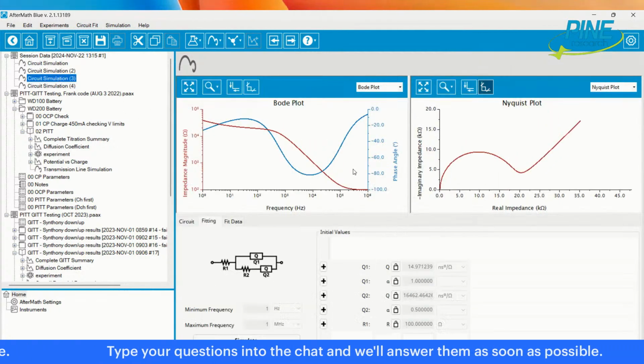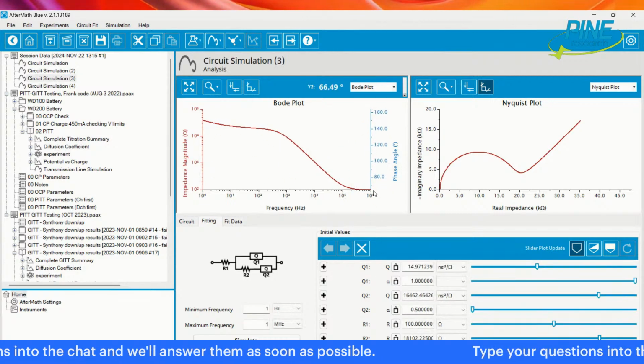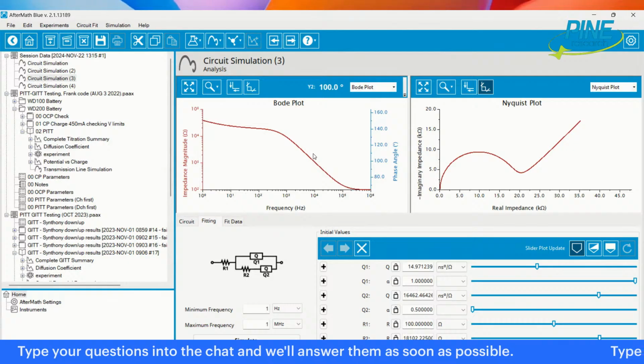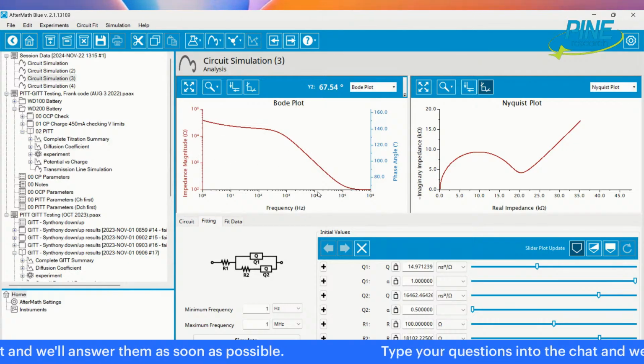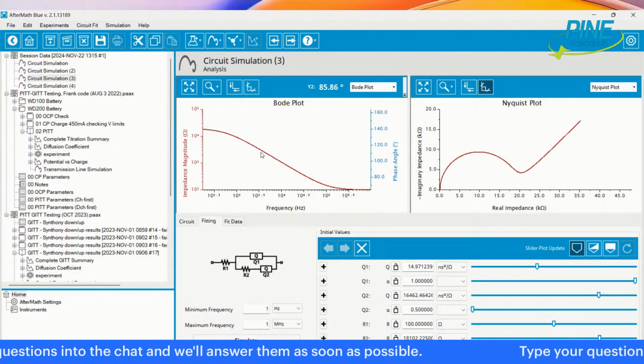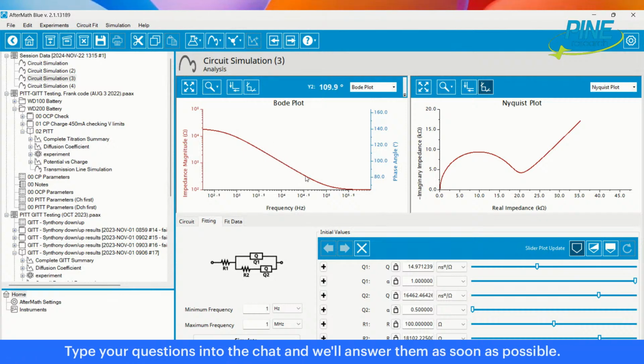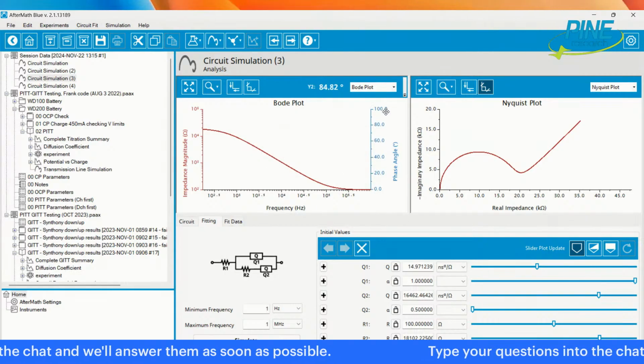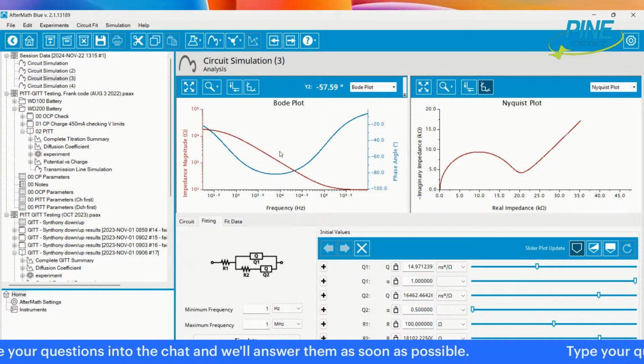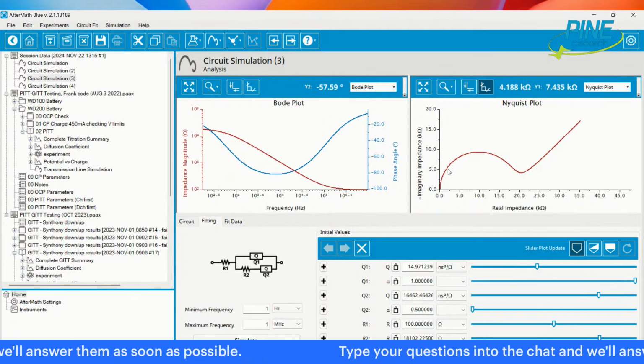Now, the impedance magnitude, almost all the time, unless you have an inductive weird thing, will always go up as the frequency goes down. It's typically logarithmic. When you have a portion of your impedance magnitude on your Bode plot where it's a straight line going up as the frequency goes down, that is the behavior of a capacitor. You can see that it roughly correlates with the peak. The bottom of the peak of the phase angle correlates with this straight line. That's where it's most capacitive. That's basically the top of this semicircle, where the y-axis is the greatest. It's mostly out of phase.